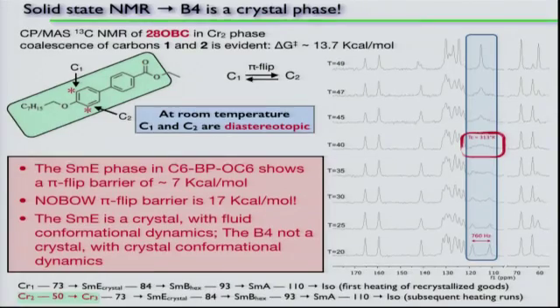That happens. It happens in crystals of amino acids with benzene rings, and it happens in any crystal that has aromatic rings. Okay? So in the solid-state NMR, this helical nanofilament phase, the molecules are thinking that they're in a solid. Okay? That's what this says. The smectic E, of course, you can't say anything about the smectic E here because you already have a singlet. You heat up into the smectic E, it's going to stay a singlet because the flipping is already happening too fast.